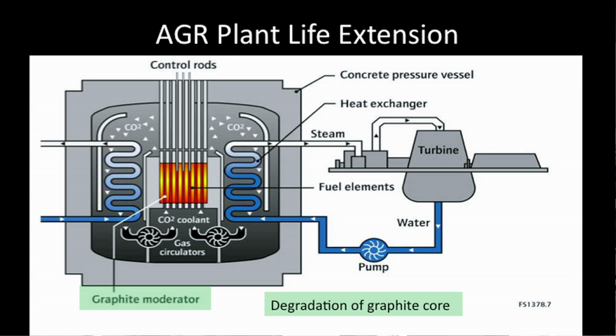If we look at a schematic of an advanced gas-cooled reactor, it looks slightly different from a pressurized water reactor. And that's because we don't use water to transfer the heat. We actually use gas. We actually use carbon dioxide to transfer the heat. And these operate at much higher temperatures, as you'll see in a moment. But the thing I want to point out is there's graphite in these reactors. And the graphite helps to moderate the nuclear reactor. And it's also a structural component. It's important that the graphite core remains intact.